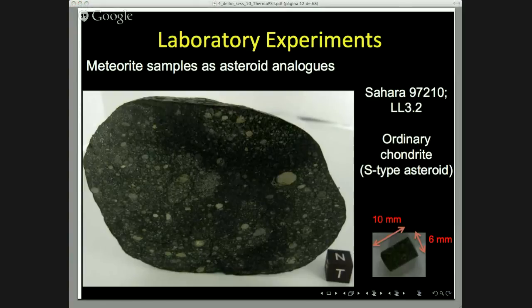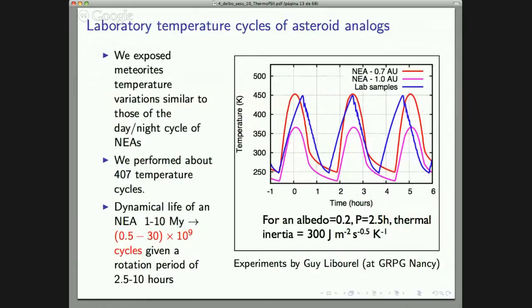So these are the cycles we did. The blue is the cycle done in the chamber, and the red and the pink are typical cycles of near-Earth asteroids. So it's not exactly the same, but it's not too different. The thing is that we did only 407 cycles, whereas a rock on the surface of an asteroid can go through billions of cycles.